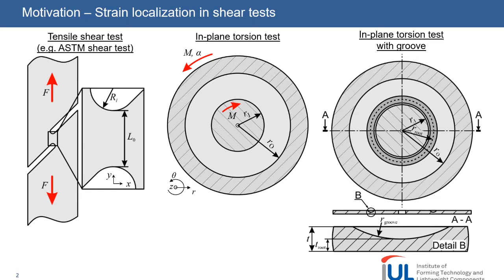Several shear tests are used for the characterization of flow curves at high strains or the fracture strain under simple shear stress state. Shear tests achieve high equivalent strains since there is no plastic instability such as necking. My today's talk focuses on the illustrated shear tests.